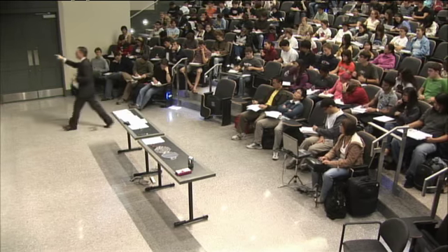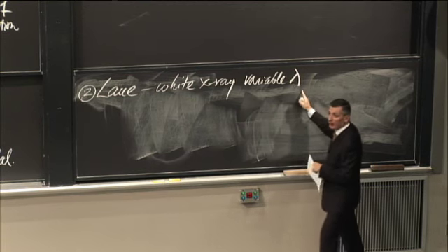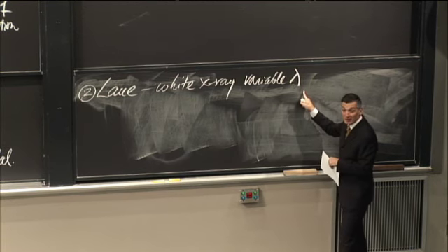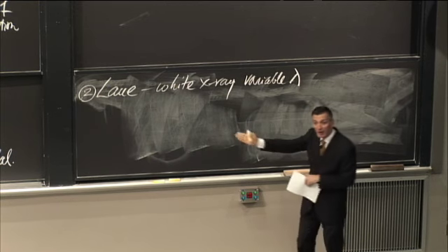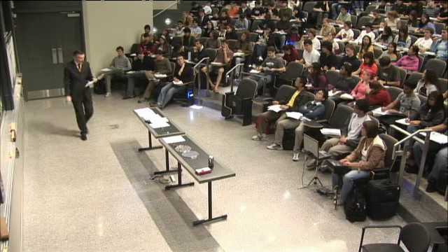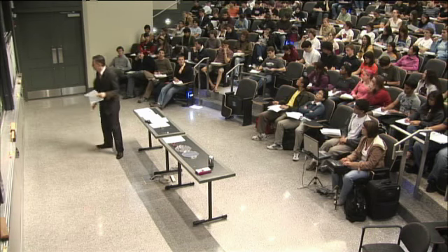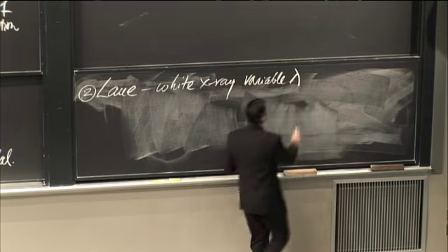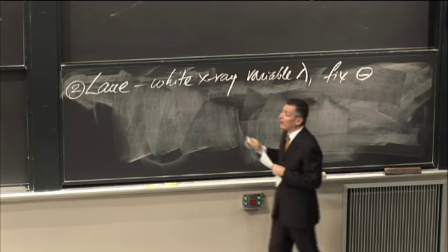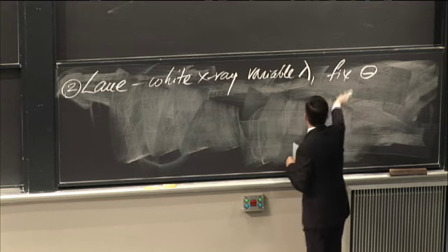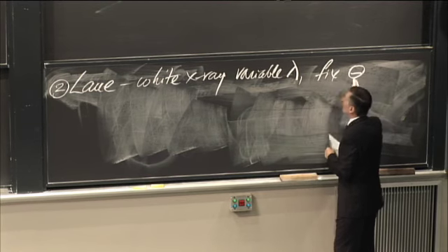But if I want variable lambda, where do I go for variable lambda? I suppress the lines and I go for the Bremsstrahlung. So now I've got lines varying all across the X region of the spectrum. So I use variable lambda and I fix the angle of incidence, whereas with diffractometry, I use a single value of lambda and vary the angle.